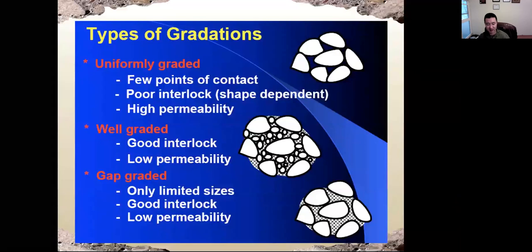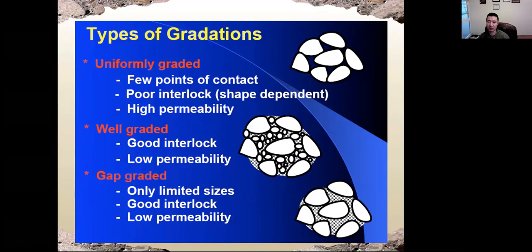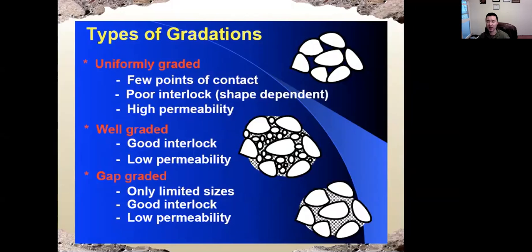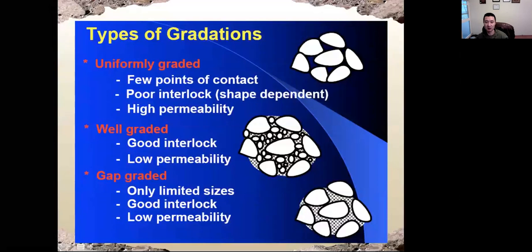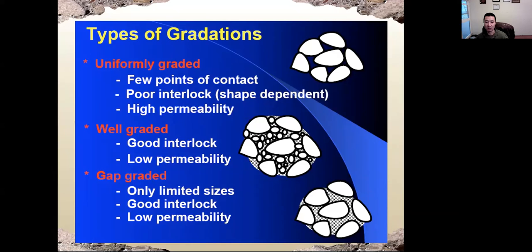All right. Next, let's talk about the gradation of asphalt concrete aggregate. Gradation is very important for asphalt concrete. It is actually more important compared with the gradation for Portland cement concrete. The major reason is that for Portland cement concrete, the cement paste is very strong. It can take a lot of load. But asphalt binder is semi-rigid. It's kind of soft, so it cannot take the load by itself. So the load transfer depends on the gradation, or the interlock between the sand and the coarse aggregate. That's the reason why gradation for aggregate in asphalt concrete is very, very important.